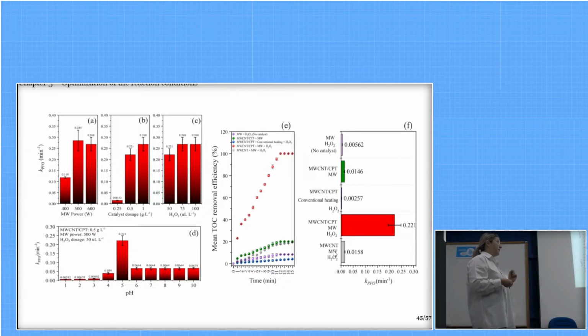Then we tested the synergy between these parameters by analyzing the total organic carbon removal. So we tested a system where we only used microwave and hydrogen peroxide with no catalyst. Then we tested the novel catalyst with microwaves without hydrogen peroxide, the novel catalyst with conventional heating and hydrogen peroxide, the proposed system with the novel catalyst, microwave heating and hydrogen peroxide, and we tested the pristine multi-walled carbon nanotubes. Here it is possible to see that there is a clear synergistic effect between these three variables at the optimized pH.